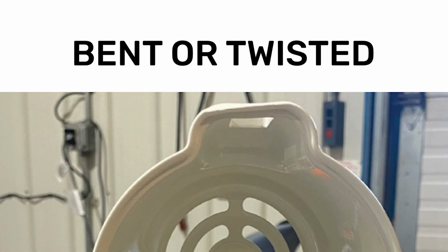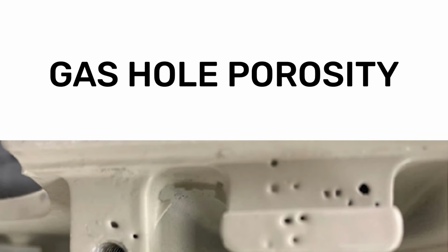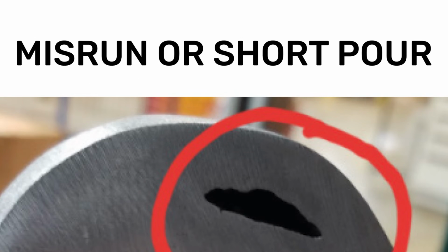For example, even though you have enough draft on your casting, the mold ejector pins could be poorly placed, and that gives you bent or twisted castings. Or the gating system feeds the metal too fast, and that creates a lot of turbulence like we talked about earlier, and that gives you porosity defects. Or even the exact opposite, the gating system feeds the metal way too slow, and it solidifies before it can fill the cavity, so that leaves you with more misruns or short pours.